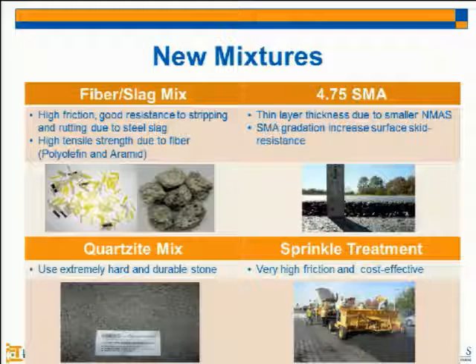The second one is 4.75 SMA. For the last couple of years, NCAT and some other states developed the 4.75 dense graded mix. If we have a smaller nominal maximum aggregate size, we can reduce the thickness. Usually for dense graded mixtures, the minimum required layer thickness is 3 times the nominal maximum aggregate size, and 4 times for SMA mixtures. So if we have a small nominal maximum aggregate size, we can reduce thickness. So this is the concept of the